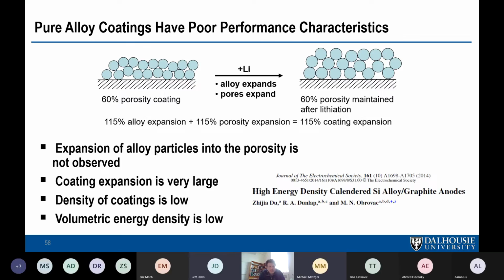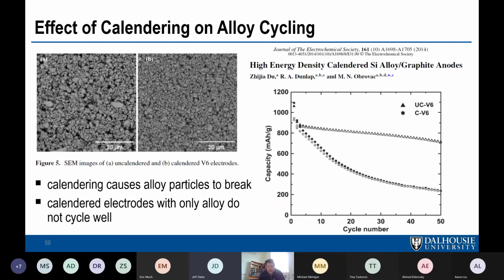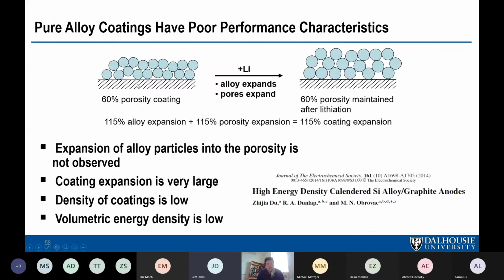Okay. Thanks. I have a question here as well. Would the situation change if we had a bimodal distribution of particles, so smaller particles that go into the pores of the bigger ones? Oh yeah, you can reduce coating porosity by using a different particle size distribution. That's true, but you can never get down to what you need for a coating, which would be 15 to 20% porosity. You can't get that level just by coating without applying any pressure on top.